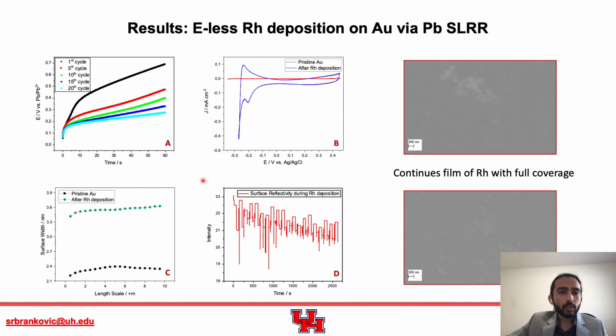So, in terms of results for this experiments, here graph A shows open circuit potential for rhodium electroless deposition from cycle number 1 to 20. And we can notice that eventually open circuit potential is decreasing as we start to deposit more and more rhodium on top. This graph B here shows that rhodium, which we have deposited by electroless atomic layer deposition method, is catalytically active. And the graph C shows roughness from pristine gold to after 20 cycles of rhodium deposition. So we observe similar trend that surface roughness is increasing after a few deposition cycles. And at the same time, surface reflectivity is decreasing as well.